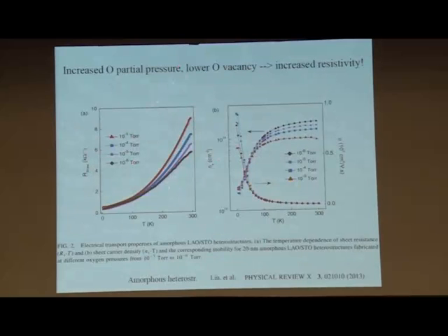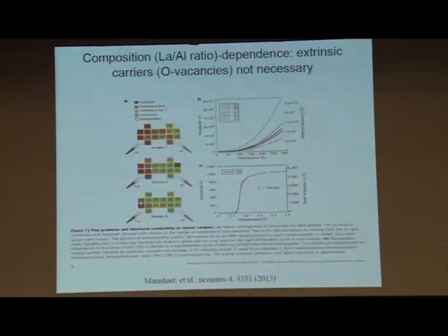The other interesting thing here, a point that he was also mentioning, is that the more oxygen the better the sample is, the worse the conductivity in this metallic region. So you need a bit of disorder to make it a very good conductor. It's just opposite to what normally happens in bulk. There is a paper from, again, almost every paper you can say Mannhart's paper here, but it's almost true. I have actually checked. Triscone and Mannhart are authors in almost all papers that come out.